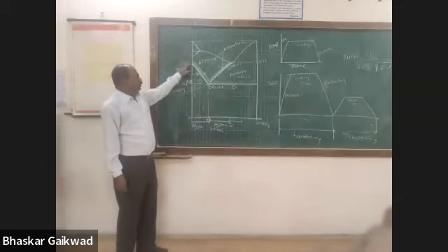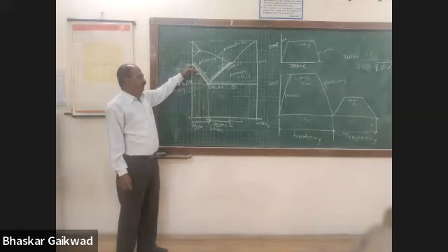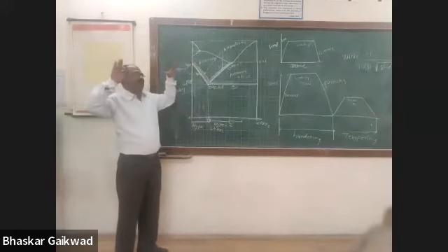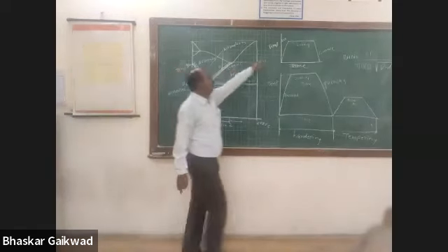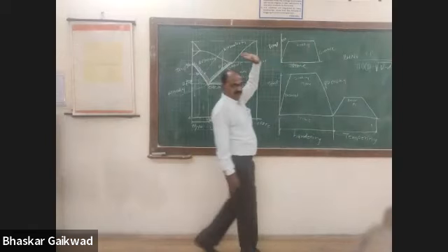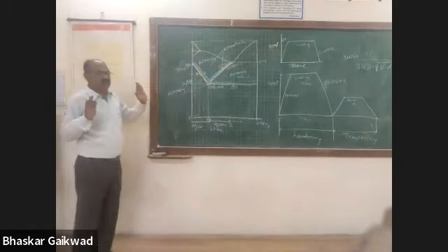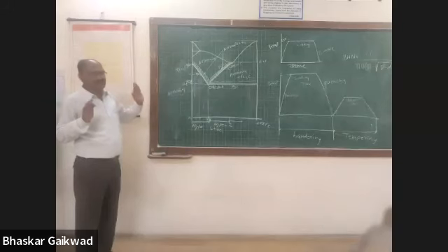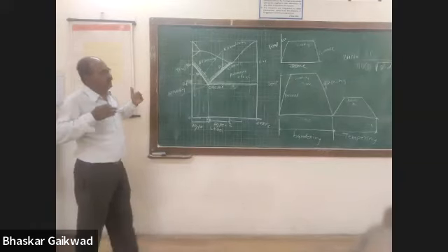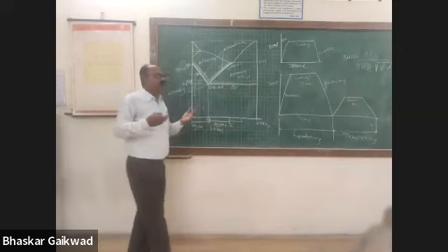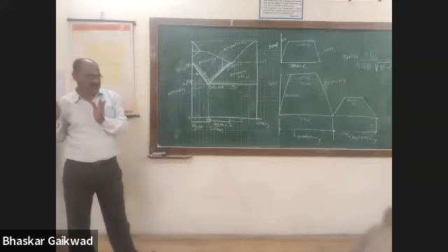Okay. After crossing that temperature, you can keep that component in the furnace without changing temperature. Means a constant line will be there. This temperature will remain constant. That is called soaking time. And that soaking time is 1 hour for 1 inch diameter of the material. Once that period is over, then you can turn the furnace off.